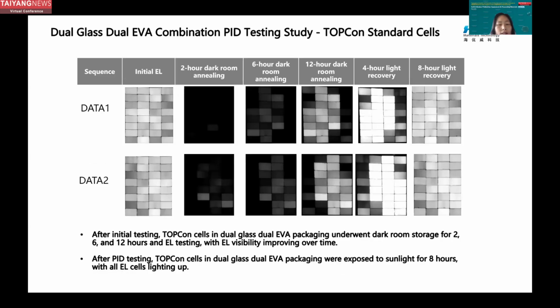This data is from an experiment performed with a combination of the improved EVA and a regular TOPCon cell. The power shows a big attenuation. As the annealing time lengthened from 6 to 12 hours, the EL was being lit up. After the module came out of the dark room, we put it outside for 4 and 8 hours. We can see that the entire EL has returned to its original state at 8 hours.